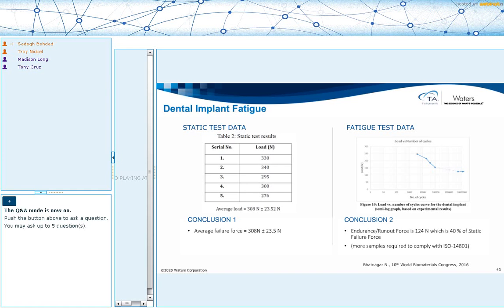Then they took 80% of that, so that would be the first stress level that you're testing at on the right. So this is a load of around 240 newtons. They start there. They tested a couple of samples. The samples broke, so they lowered the stress level to another one. And you can see they start somewhere around 5,000 cycles, right? And then going from 80% to eventually 40% of the static failure load, you can see that they were able to reach 5 million. So going from 5,000 cycles to 5 million cycles by reducing the stress or load to a half of where you started, this shows you that this behavior is not really linear.